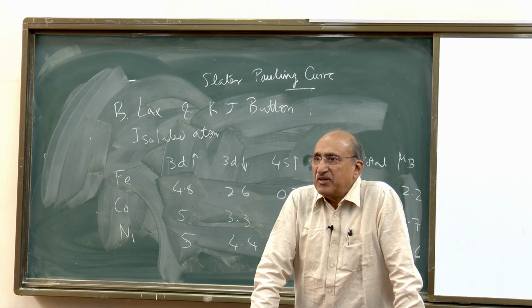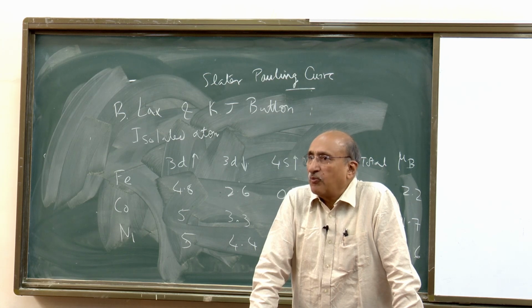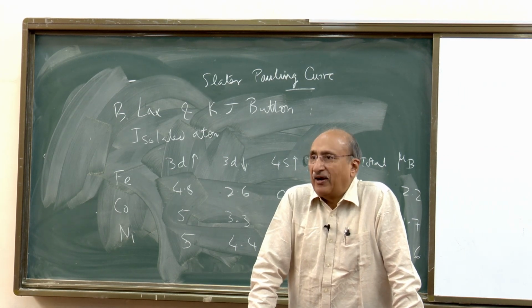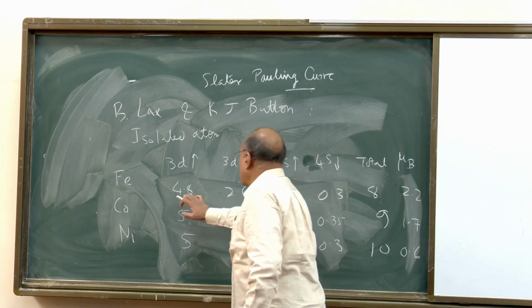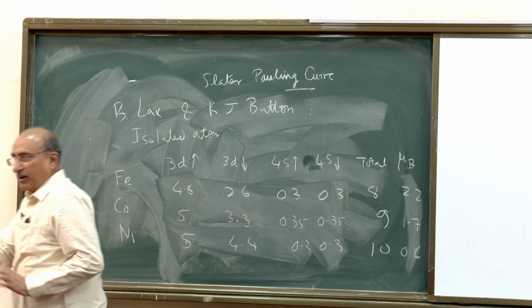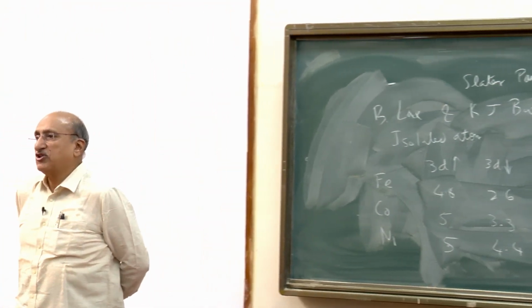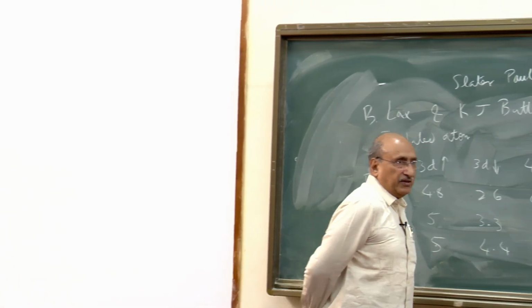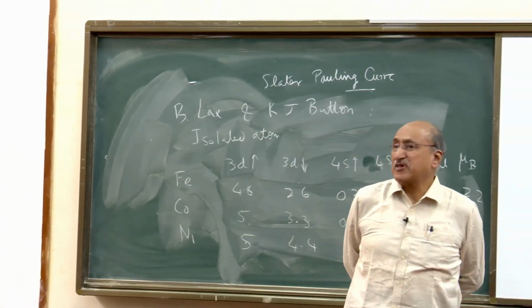A strong magnet means the splitting between spin up and spin down band has increased so much that one of the bands is completely filled. So according to this, because cobalt's 3D up band is completely filled, these are called strong ferromagnets. So this is a terminology which is often used and which is often confusing when people are working in the case of metallic systems, especially alloys.